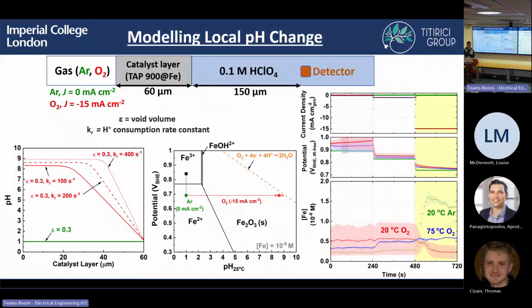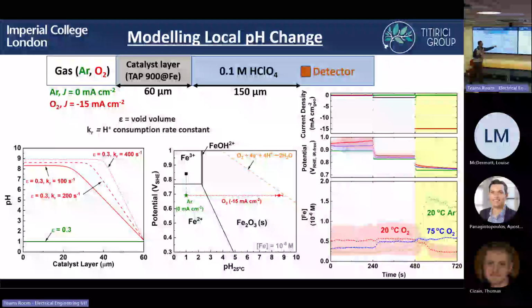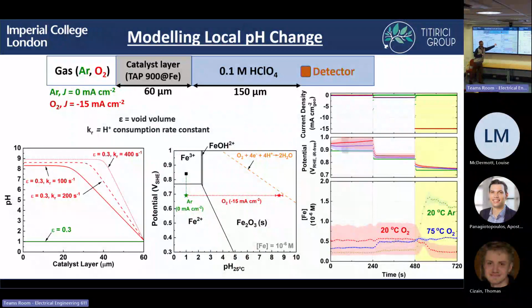So then will that count as catalyst being utilized if there is no reaction? No, I don't think the catalyst is being utilized. Basically, as you're increasing the pH, you're shifting the potential closer and closer to the potential for oxygen reduction. So from anywhere from say pH 5, it's maybe not being used. So then over half your catalyst layer isn't being used. You're just using this part.